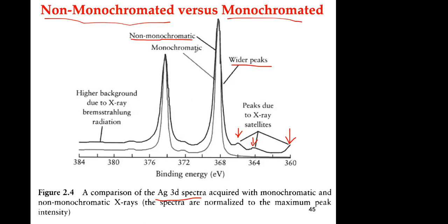When you use a monochromatic source, the peak is thinner. The full width at half maximum is much better. And you don't see these peaks because those photons didn't go through the quartz. They were removed. Only the K alpha of aluminum went through, and that's the only one that excited the sample. The other photons didn't excite.